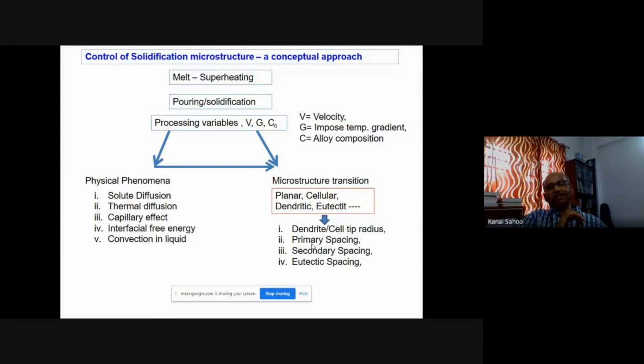So you have to really take care of your solidified microstructure. Here, the three process variables you have to take care of are velocity, temperature gradient, and alloy composition. Of course, several physical phenomena are involved: solute diffusion, thermal diffusion, and all these listed here. The microstructure transition may be planar, cellular, dendritic, or eutectic. So with the dendritic structure, how to reduce the dendrite, the cell tip radius, the dendrite tip, and how to decrease the primary spacing, the secondary spacing, and the eutectic spacing, I'll highlight in my talk. Because in all cast structures, the dendrite tip is very detrimental. The tip of the dendrite acts as a stress raiser, thereby giving very low mechanical properties.